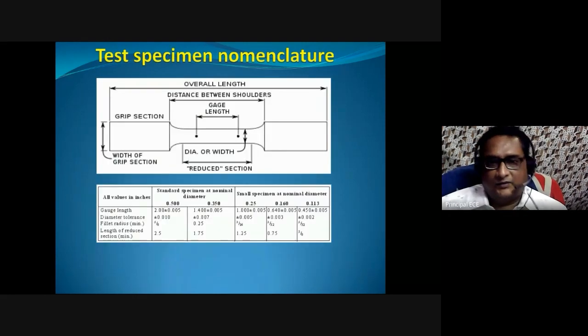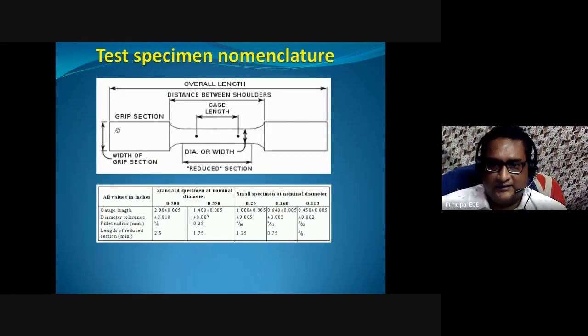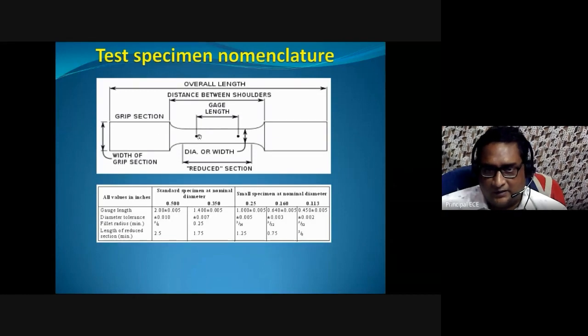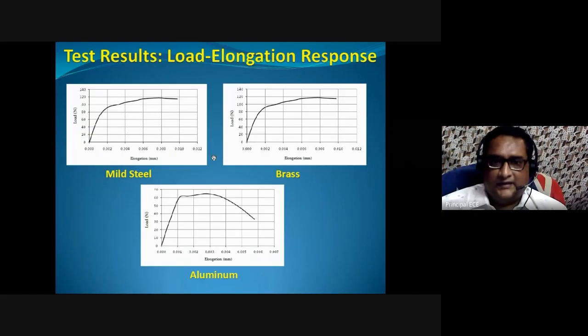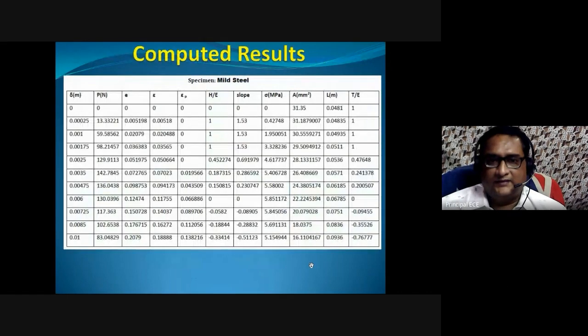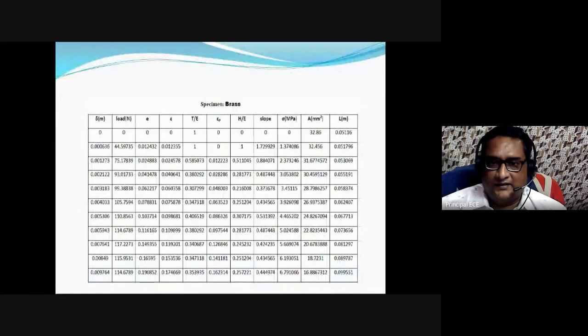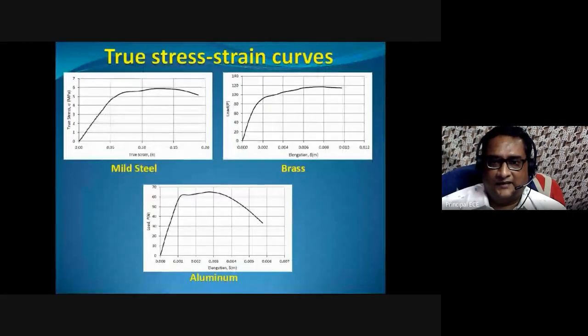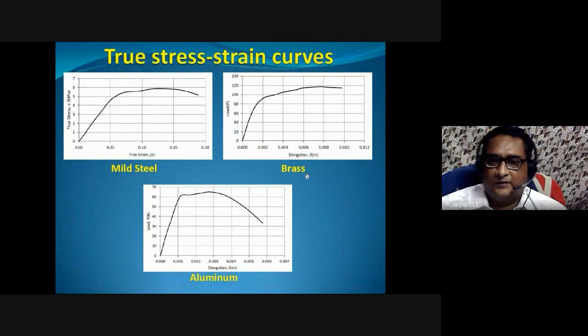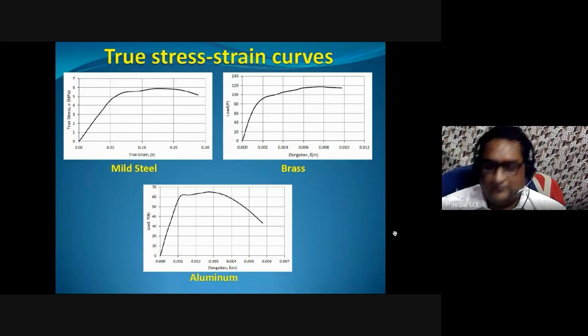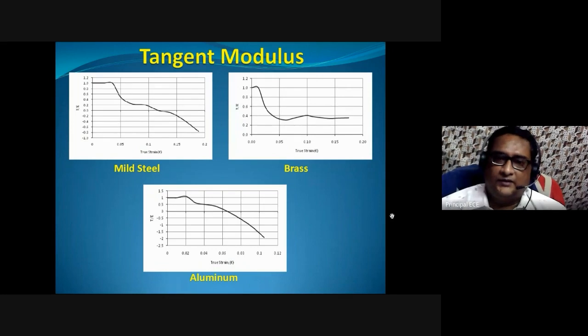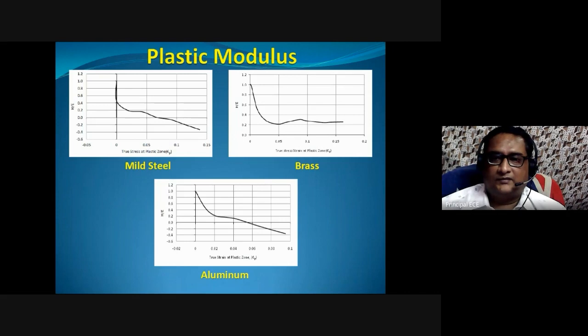This is the specimen. This is the grip section, gradually tapered to the gauge length. This is the load versus elongation. We tested three materials: mild steel, brass, and aluminum, and these are the computed results. We computed some parameters and plotted the true stress-strain curves for mild steel, brass, and aluminum. The tangent modulus we derived from these curves. They show a non-linear pattern, and so does the plastic modulus.